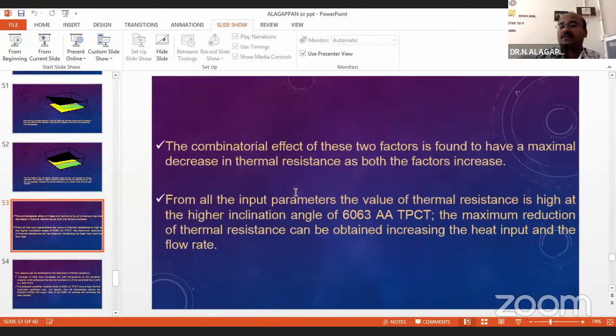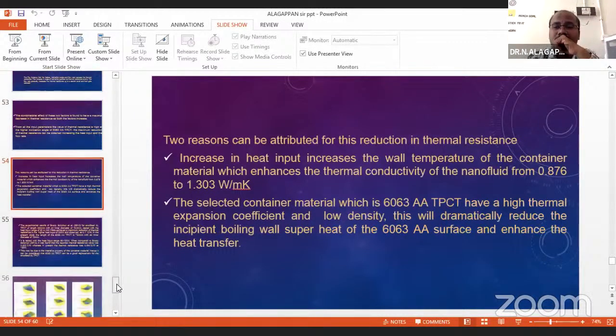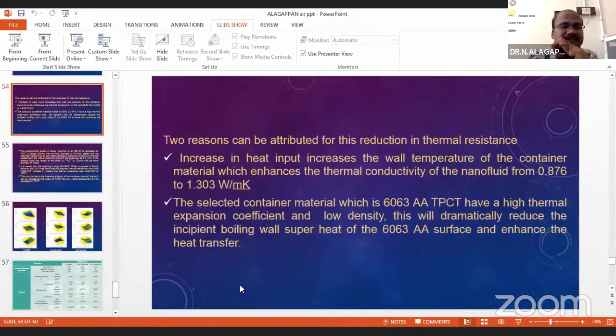The combined effect of thermal resistance for both factors, from all the heat input parameters, the value of thermal resistance is high at a higher inclination angle of 6063 AATPCT. The maximum reduction of thermal resistance can be obtained by increasing the heat input and flow rate, which means if you are increasing the heat input to your pipe, your thermal resistance gets decreased, which means the heat transfer of your pipe is more. And similarly, if you are increasing the flow rate, again, you get a good result in thermosiphon. Next, sir. Next slide, sir.